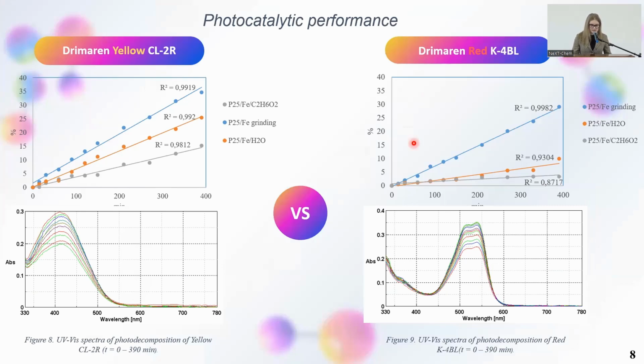The photocatalytic styrene acrylic coatings were comparatively tested for the degradation of reactive dyes under visible light radiation. Experimental data suggest that the photocatalytic activity is essentially increased due to the processes that are generated at the surface of titanium dioxide. However, the coating obtained by wet grinding degraded the reactive dyes more effectively than the other coatings, about 1.3 times faster than the coating synthesized with water, and about 2.3 times faster than the coating synthesized with ethylene glycol.